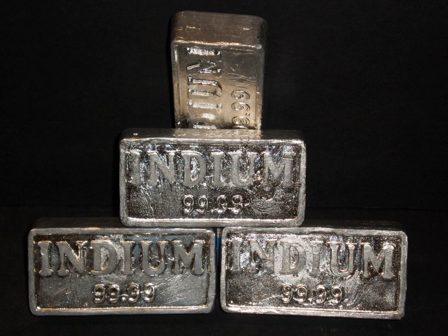At standard temperature and pressure, indium crystallizes in the face-centered tetragonal crystal system in the space group I4/mmm, lattice parameters a = 325 pm, c = 495 pm. This is a slightly distorted face-centered cubic structure, where each indium atom has four neighbors at 324 pm distance and eight neighbors slightly further, 336 pm.